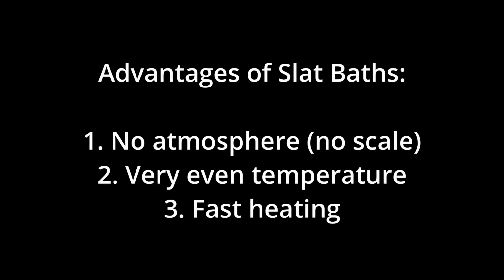But you probably want to know why use a salt pot at all. Well, they do have a few advantages. One is that you don't need to protect the steel from oxygen. When you stick the steel in a molten salt, there's no atmosphere. It's just in molten salt. So there's no oxygen to form any scale on the steel or to lead to decarburization. You don't need any coatings or any foil. You can just stick the steel directly into the molten salt and then pull it out and quench. So very easy, very convenient.